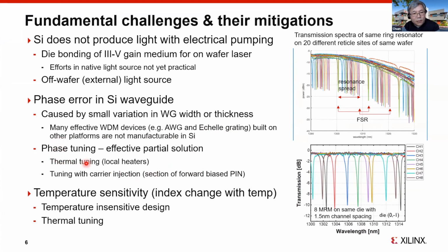The way to get around it, of course, is to do phase tuning. This phase tuning works on some relatively simpler devices, such as Mach-Zehnder interferometers or ring resonators. There are two ways to tune the phase. One is thermal tuning. When you change the temperature of silicon, its index changes, so you can use that to tune the phase of a silicon interferometer or a silicon ring resonator. Another way to tune it, of course, is carrier density tuning through carrier injection into silicon.